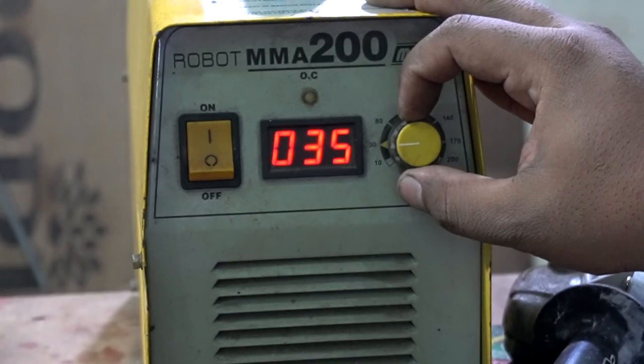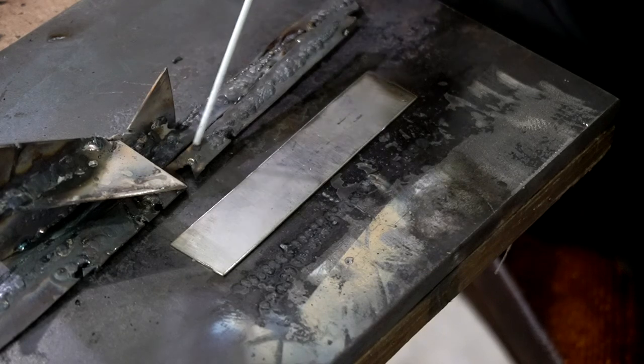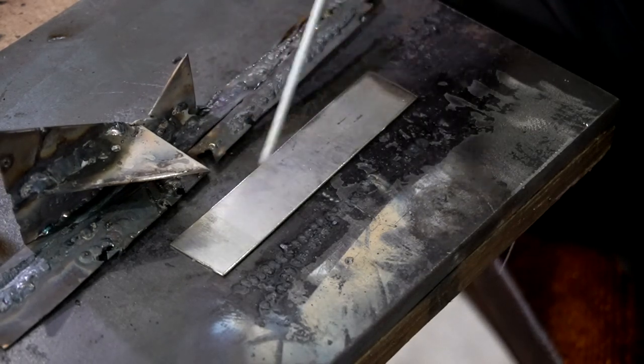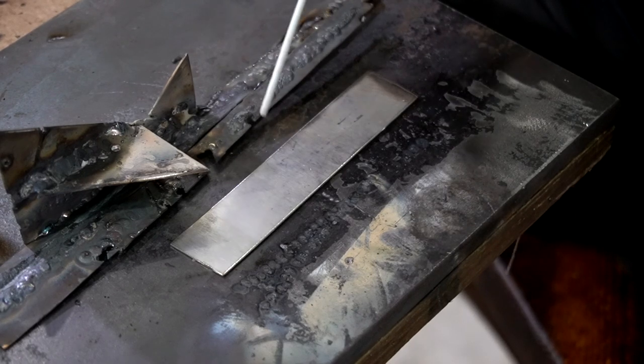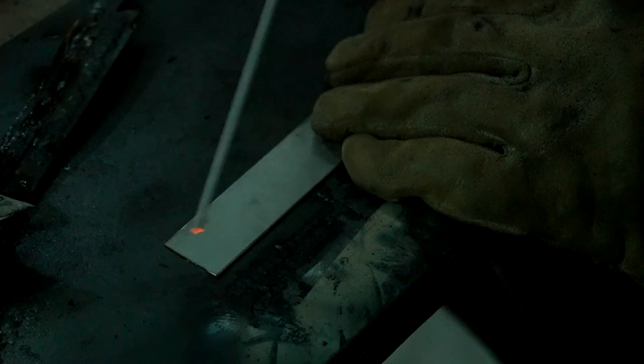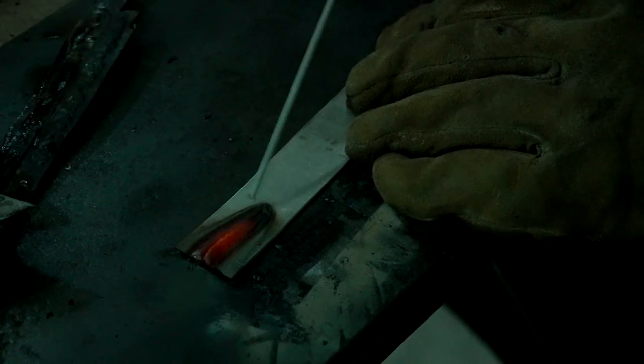I found this to be optimum, and along with that I am keeping a piece of scrap sheet, because I am first going to create a spark over that piece and then shift over to my main workpiece. The problem with this electrode is that if it sticks to the material, it starts to glow within a few milliseconds. You can see that in the first attempt the material starts to separate because of the slow speed, but in the second attempt it's completed. But surely the material is going to warp because we are creating a lot of heat.